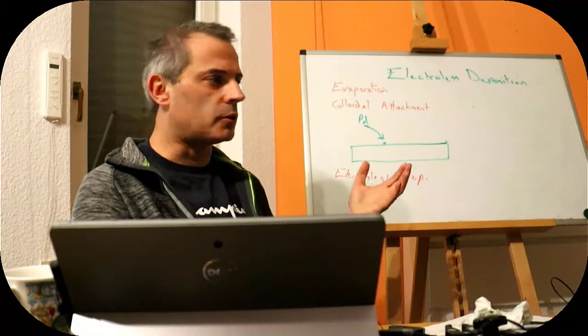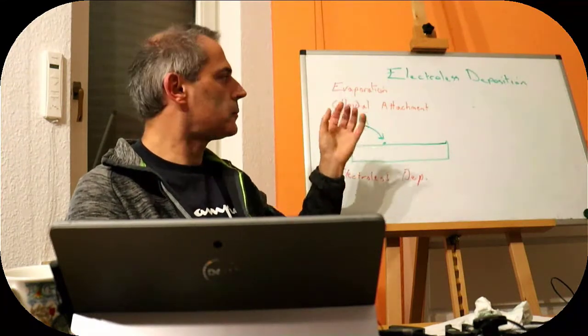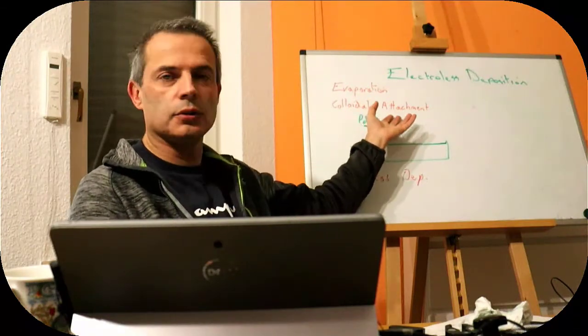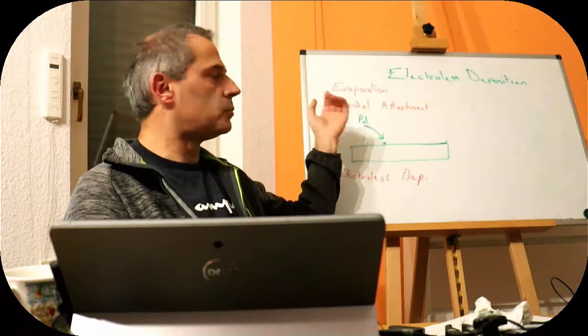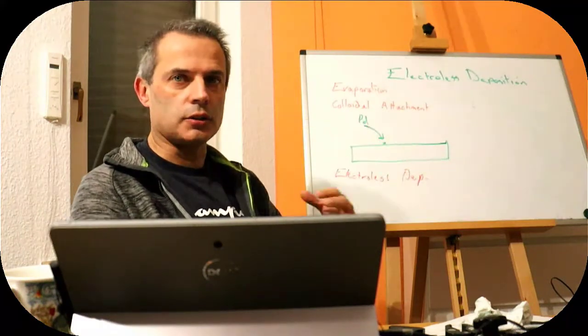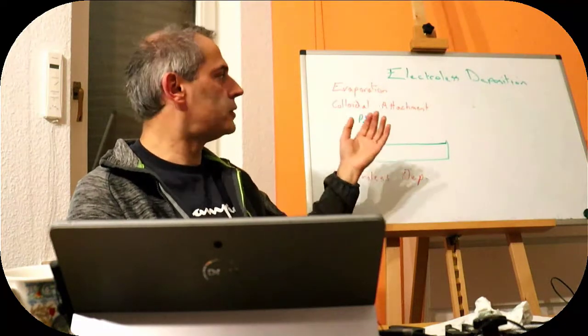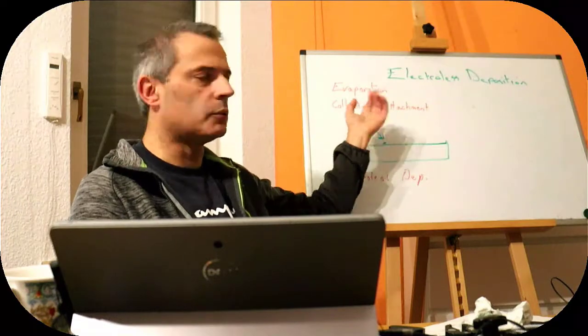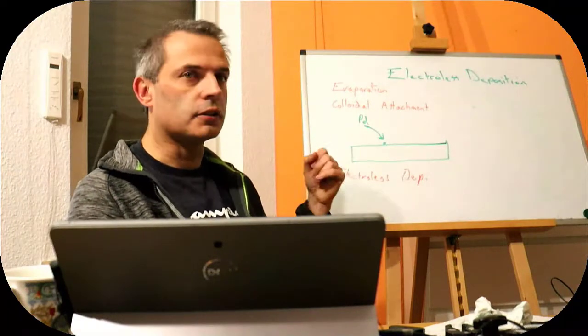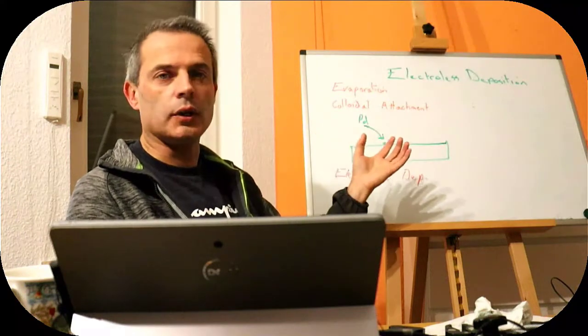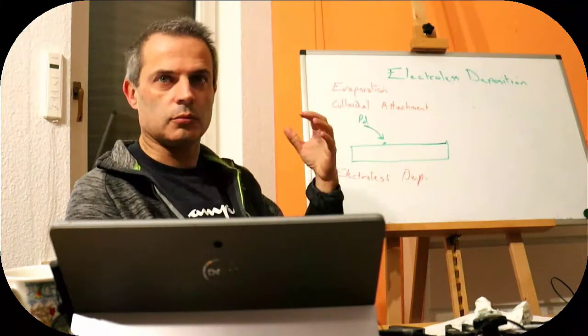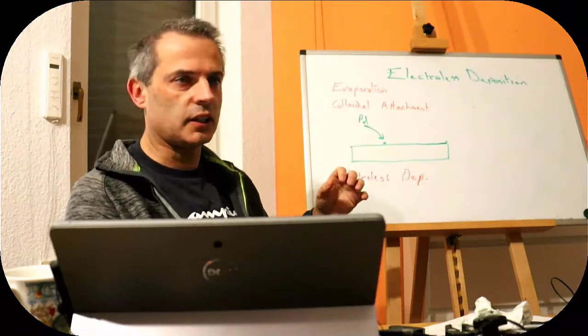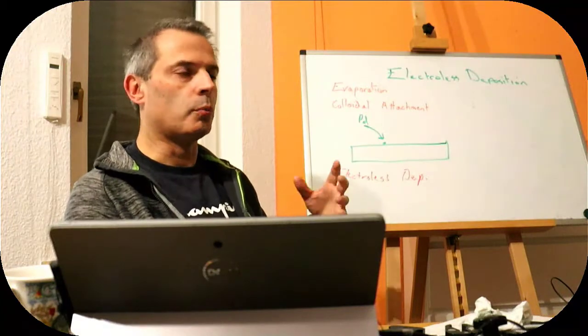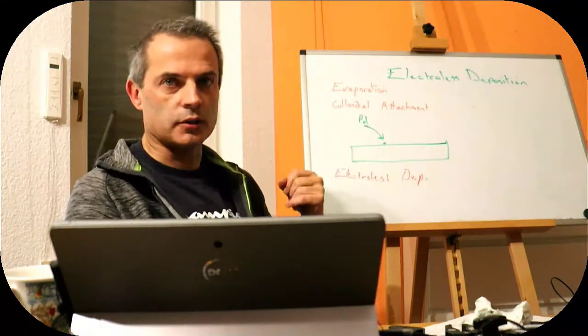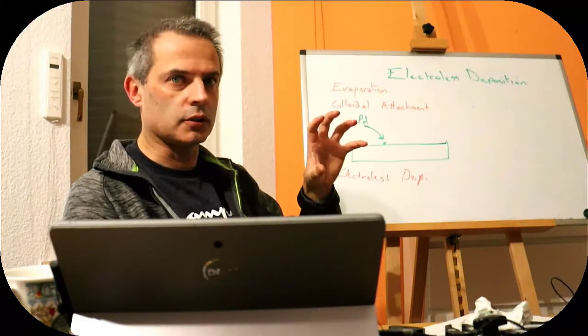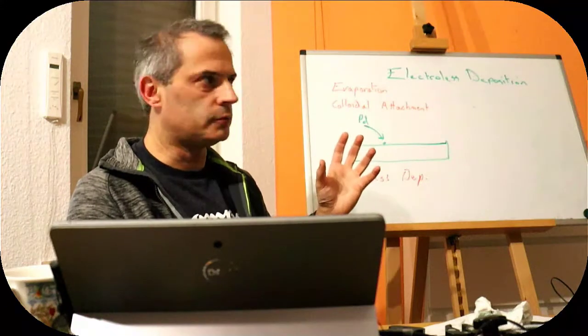We can, however, just accept that we're going to make particles and start off with particles. If we do that, we have some particles in our solution. We generate a colloid, some metal particles in solution, and we allow them to stick to our surface. That would happen first of all by electrostatic interaction, so we can make our metal particles positively charged and our surface negatively charged typically, and then we attach them. We interact them electrostatically, and then we would have to make them stick more permanently. That is easy to do. All we have to do is dry the solvent, and that causes our particles to get very, very close to the surface, and then it is more difficult to remove.